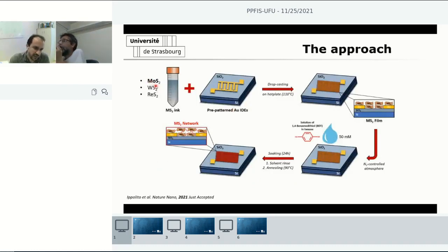So what we did was, we prepared our ink, and we demonstrated for different metal disulfide inks: molybdenum disulfide, tungsten disulfide, rhenium disulfide. We deposit on top of interdigitated electrodes, so we have the flakes spread on top of the contacts here for the electrical characterization. We expose it to the benzene dithiol solution, and after some thermal treatment to evaporate the solvent, we expect that these flakes will be bridged together.